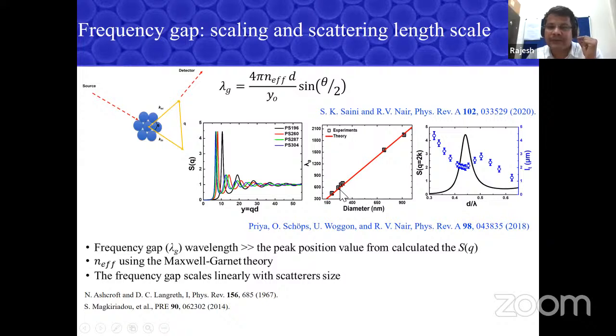If I want a gap here, I need to use this sphere diameter. And if I want a gap here, I need to use this sphere diameter. And we even estimated the scattering length scales, like the transport mean free path, and it actually shows a reduction within the frequency gap induced by the short range order.